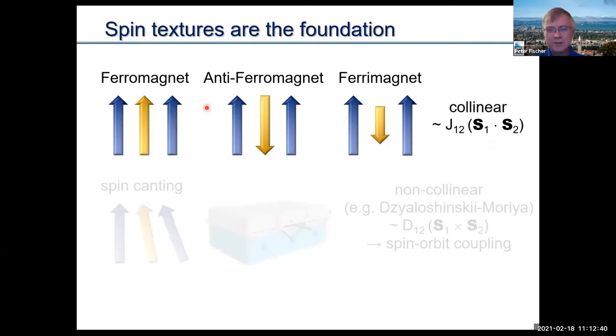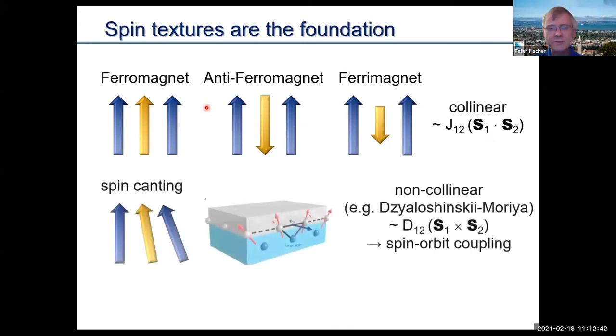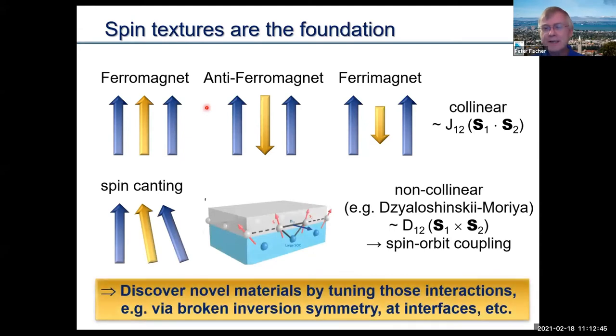Now, what is new, and this is just coming very recently, maybe over the last 10 years or so, a little more than that, but anyway, it's very exciting. So from a mathematical point of view, these two spins, you cannot just couple by the scalar product, which of course gives this parallel and antiparallel alignment, but you can also put a cross product in between. And with this, you arrive immediately at the non-collinear orientation of spins, because all of a sudden, the minimum energy of two spins that couple by this kind of antisymmetric exchange coupling, that's how we call it, because if you switch S1 and S2, this interaction changes its sign, well, you end up with a non-collinear orientation of neighboring spins in the ground state of energy.